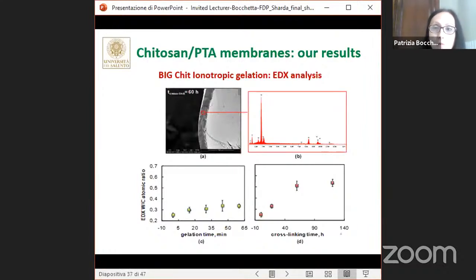The results we have discussed agree with EDX results, where we have estimated the tungsten carbon ratio. You can see that the tungsten carbon atomic ratio moderately increased in the first minutes of chitosan gelation, and after 30 minutes remained quite constant. So this is in good agreement with the slow diffusion of acid in the already formed film. It is likely that the cross-linking reaction needs low gelation rates to be more incisive.